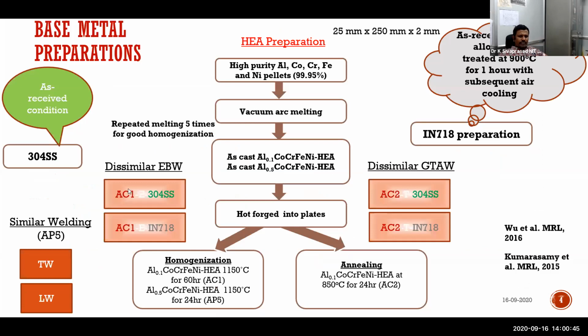Then we have taken dissimilar welding. We have done EBW of 0.1 with 304 stainless steel and 0.1 with Inconel 718 using electron beam welding, which is designated as E. 0.1 stands for AC1, 0.5 stands for APS, and like that it is designated AC2. Then TW stands for TIG welding, LW stands for laser welding. Then AC2 is the TIG welding combination. T stands for TIG here, with 304 stainless steel and Inconel 718.